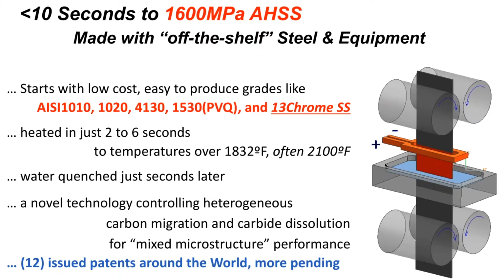What we do is we heat the steel in just a couple of seconds to temperatures above 1832, often to near 2100 degrees Fahrenheit. Now that's a little bit counterintuitive when most steel heat treating is done down around 1500 or 1600 degrees. We water quench just a few seconds later, and we have a novel technology, and our goal is to control heterogeneous carbon migration and carbide dissolution for a mixed microstructure performance.